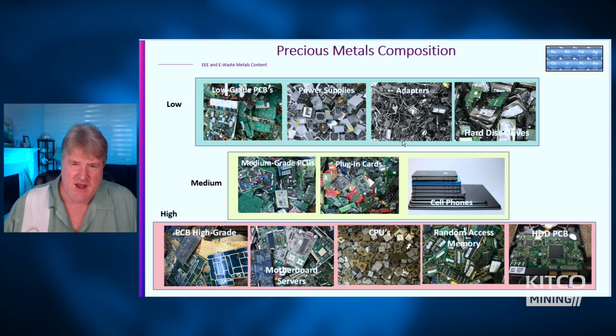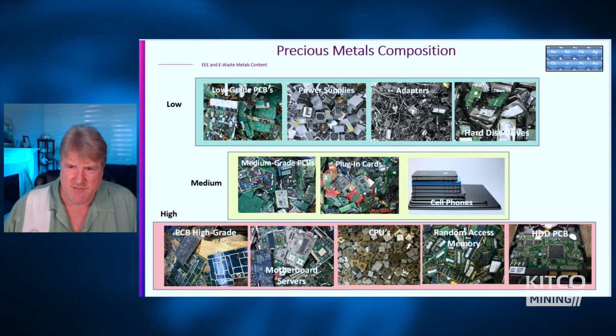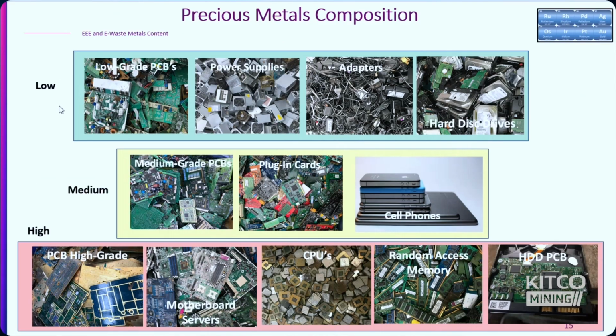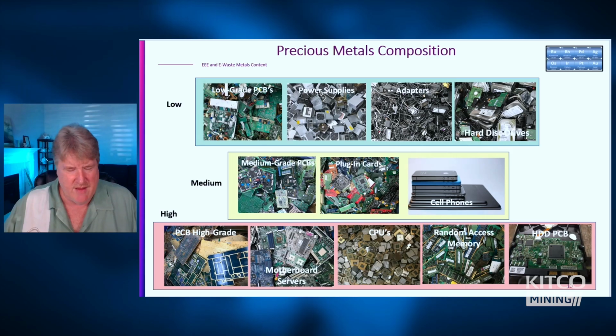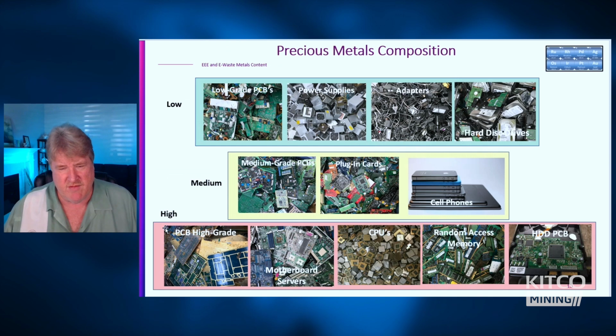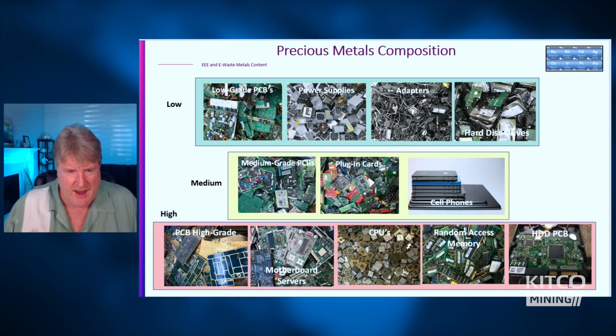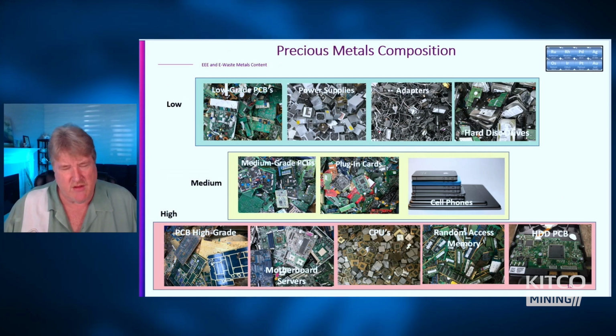And I know with most conventional e-waste guys that there's grading that you could do if you know how to separate these things. A low grade, typically 70, 75 parts per million or lower, a medium grade, which could be 150 to that 70, and then a high grade, typically over 300 parts per million, is what's treated as a high grade. And this is the really valuable stuff. And there are a number of e-waste smelters that only want to deal with the high grade, right? That's where the economics are the best for them as recyclers.